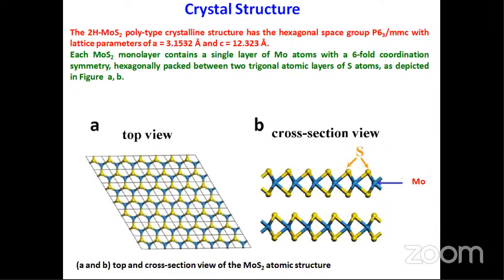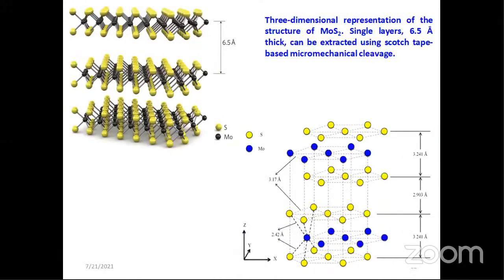The most important thing is that, due to the stacking of the layers along the c-axis, the space group is P63/mmc, and there are several types of polymorphic crystal structures in TMDCs. There are commonly five types in MoS2: 1H, 2H, 1T, 1T', and 3R. H is the hexagonal structure, T is the trigonal structure, T' is the distorted octahedral structure, and R is the rhombohedral structure. But the common structures are 2H and 1T. This is the important crystal structure of molybdenum disulfide.